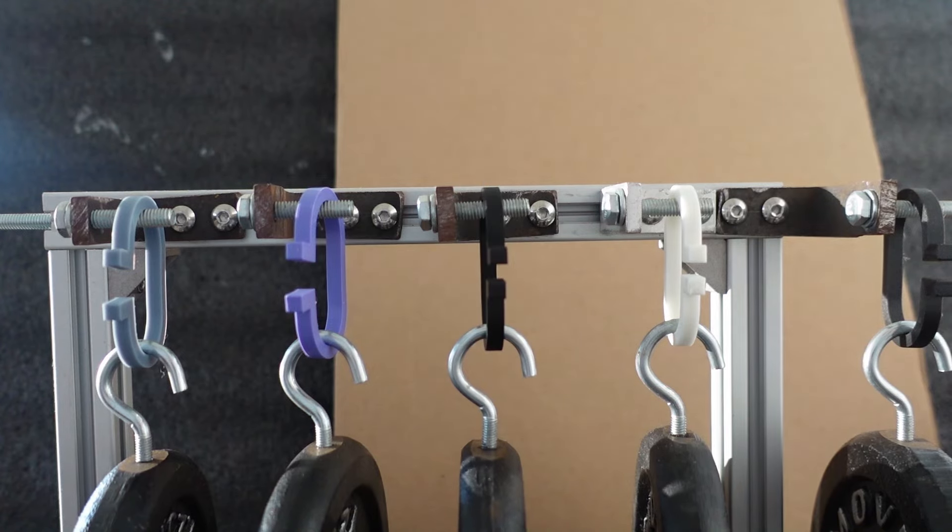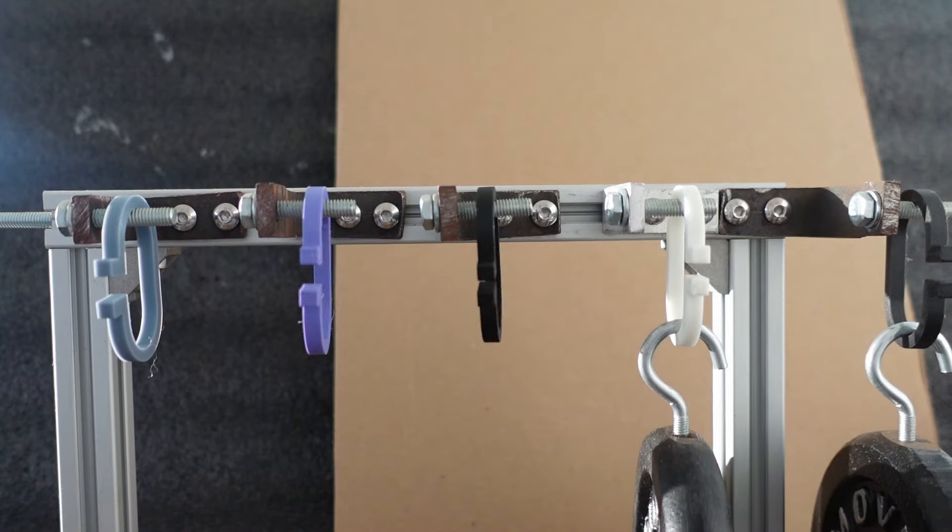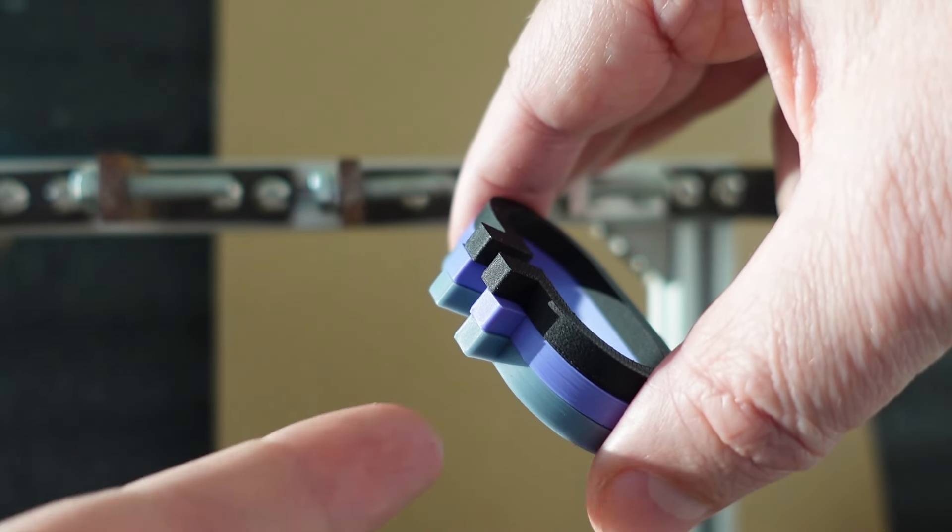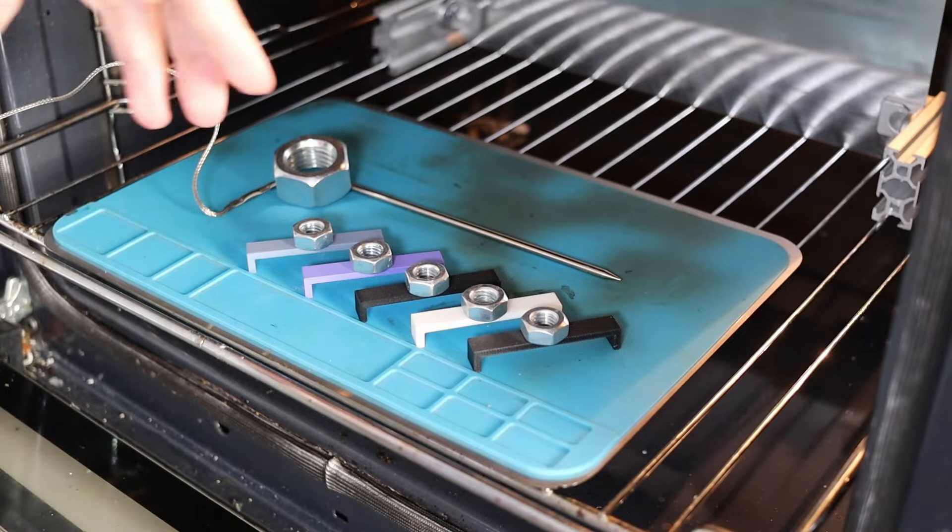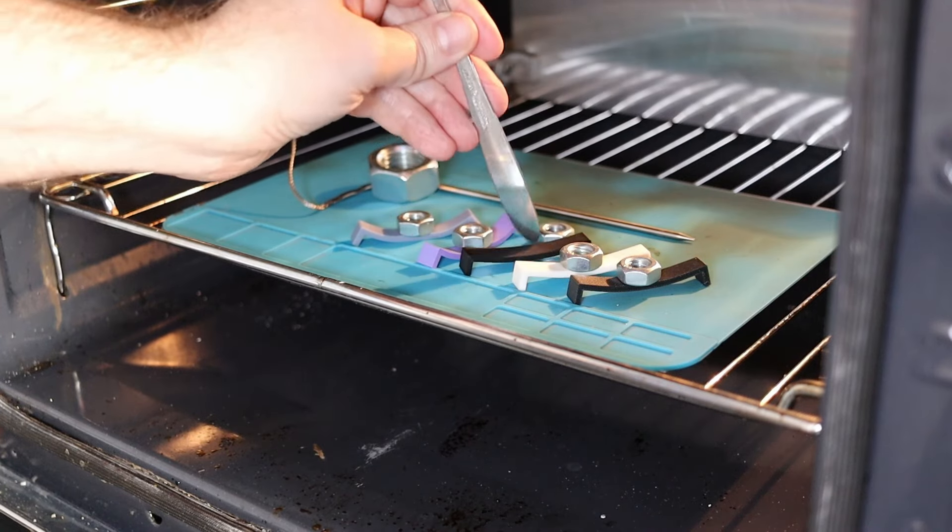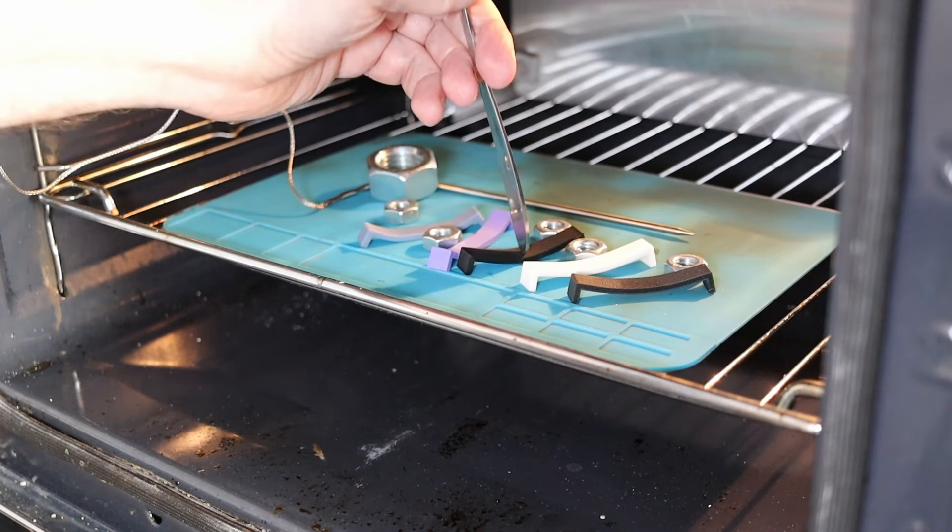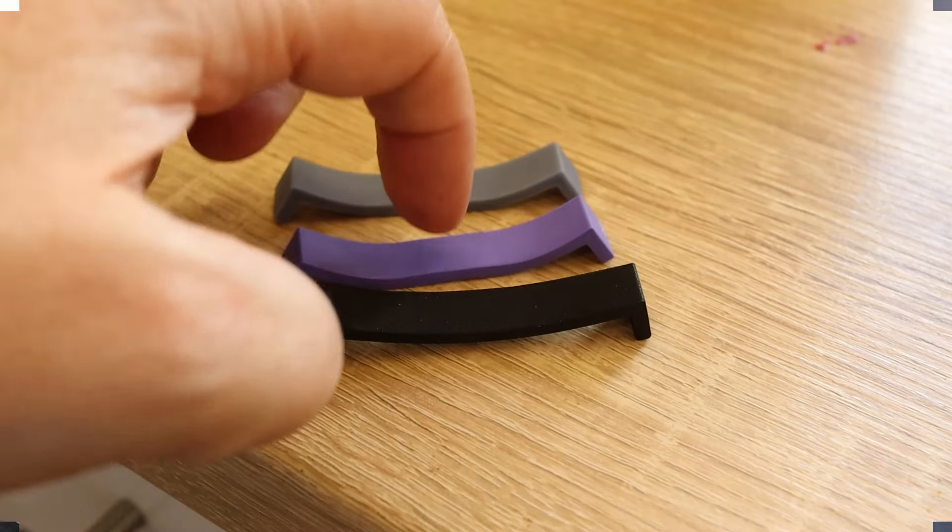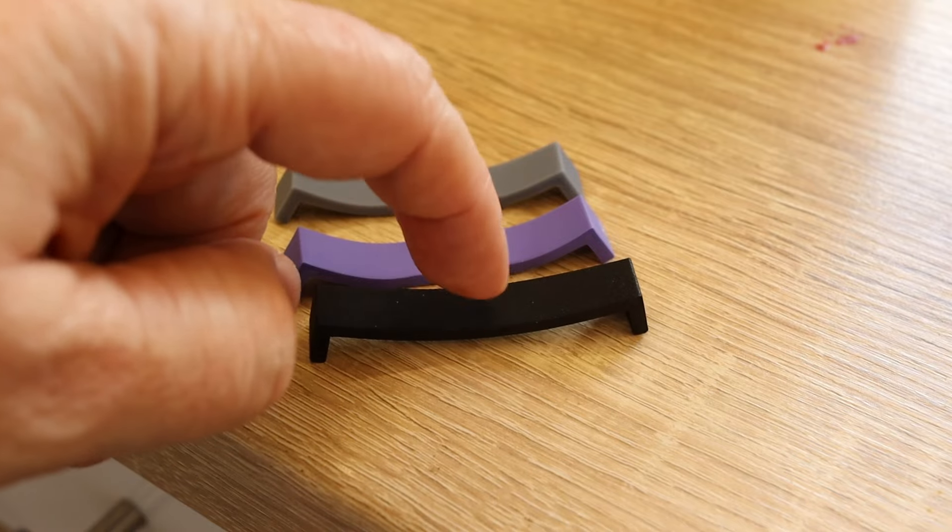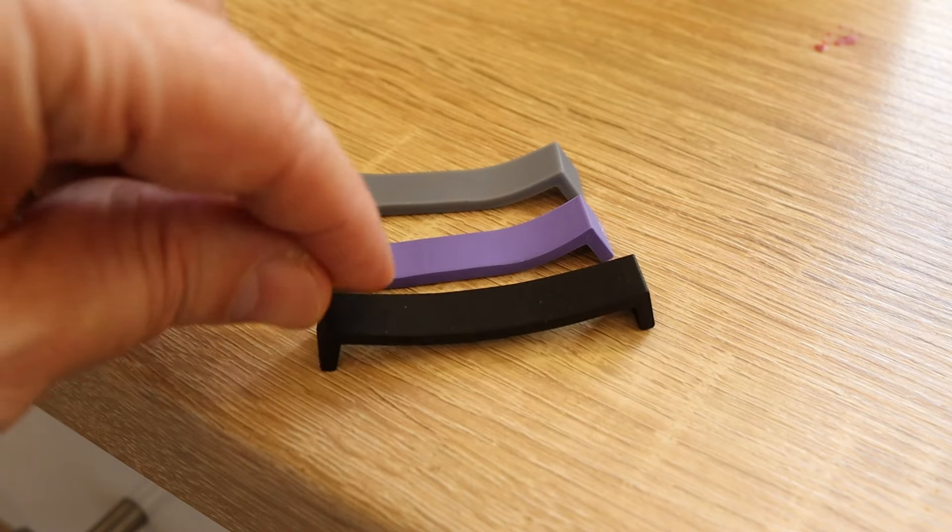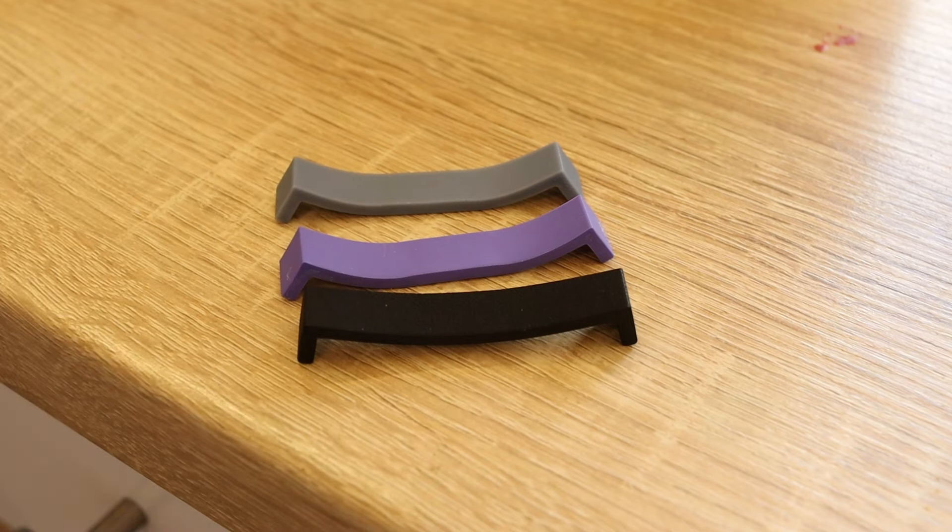And now the temperature test and these three materials are from this video. This is sped-up timelapse video and the first deformation I noticed at 52 degrees celsius and the carbon fiber started approximately at 61 degrees celsius. I will stop the experiment now because I am curious how soft they are. So those fibers help against the deformation but the material is quite soft. Now they are equally hard but it was interesting to see after the test actually the carbon fiber deformed less but it was softer compared to these two filaments so this means those fibers help with holding the position. And maybe this was annealing temperature for the other two materials.